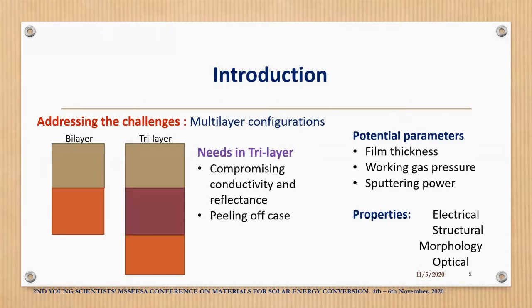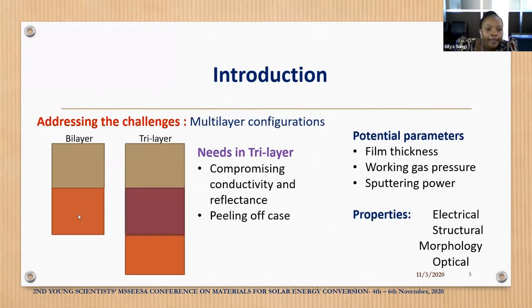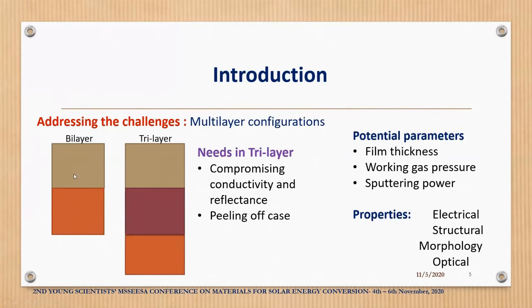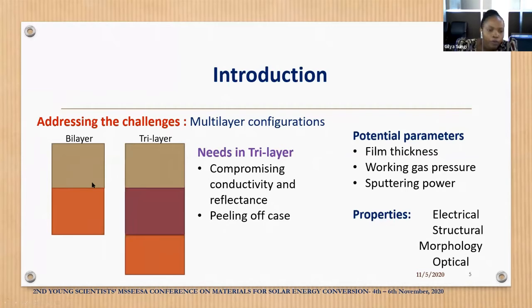To address these challenges, material configurations have been suggested: the use of bilayers and tri-layers of molybdenum. Using these configurations means that the bottom layer can be deposited with different parameters compared to other layers. In this way, bilayers have shown promising results compared to single layer, but there were still challenges of compromising resistivity and high reflectance, together with the peeling off cases.